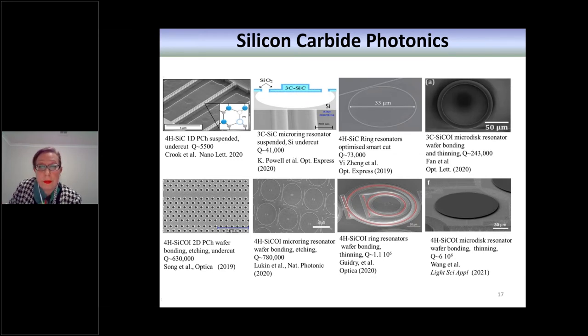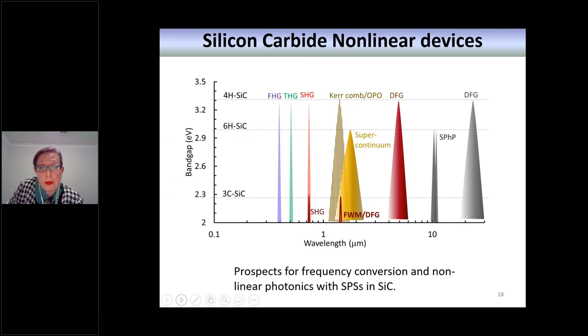From the point of view of photonics, this is quite a challenging space, because it's true that it's a good material, but there are many challenges still. As you can see, in the evolution in the last years, the cavities in silicon carbide have reached a very high Q, which is on par with what is done in diamond, but not yet at the quality of silicon. So there's still quite a bit of work to do to improve the photonics, even though there has been quite a lot of improvement, particularly in relation to silicon carbide on insulator, which has recently been optimized. And so there is probably space to reduce the optical losses in this material.